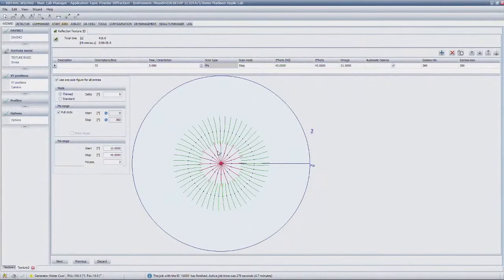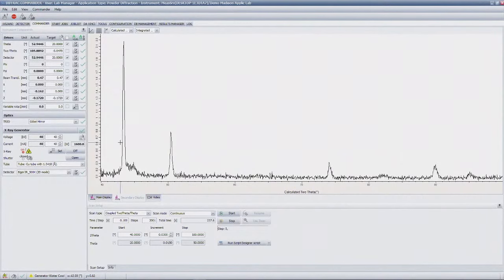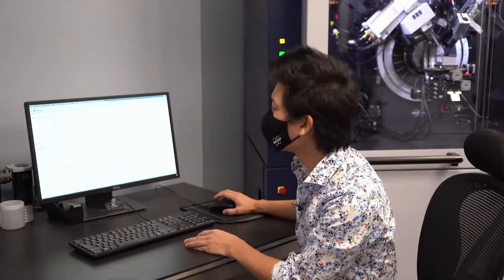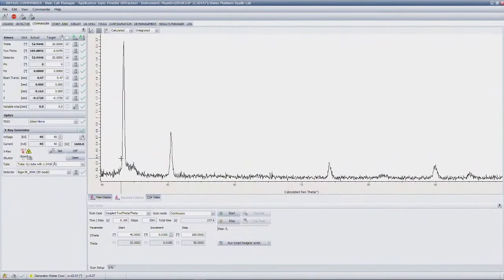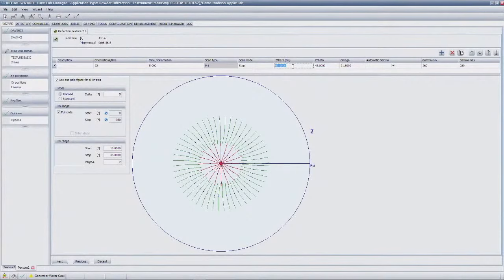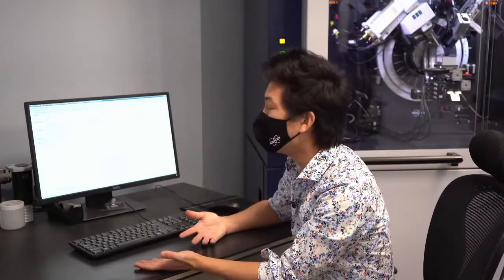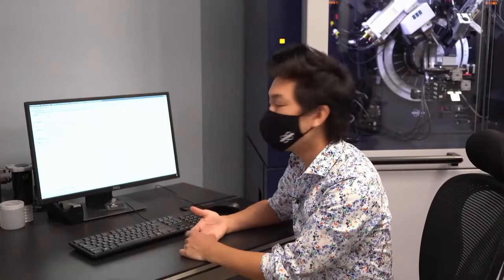Final point of this is if you do have this large coverage, one of the neat things you can do is if we go back to Commander, we can see here that we've got 2 peaks that are right on top of each other. So at this distance with the detector, about 150, 170 millimeters from the sample, we're getting about 11 degrees of coverage in two-theta data at any one moment. So what that means is we could actually park our detector right in the middle of these 2 peaks, say at 48. If we park it at 48 instead, what we can see is that we're actually able to cover all of this and get 2 pole figures, which further increases your speed of data collection because you're getting quite a bit of data all at once.